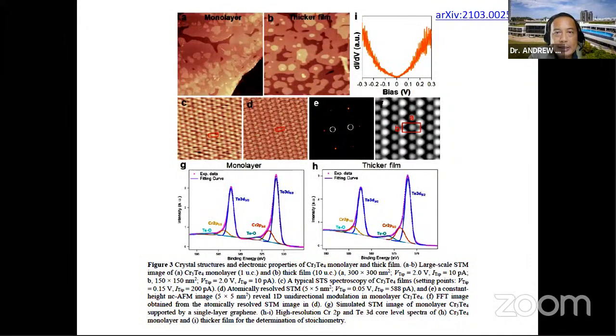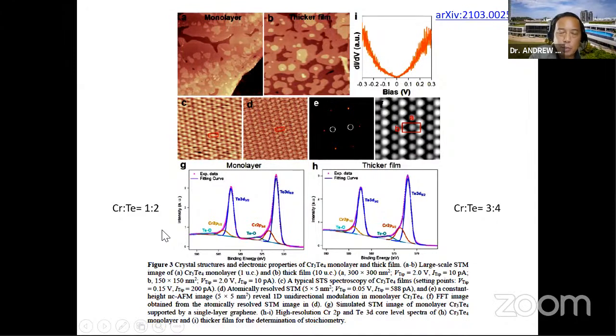And here is the XPS. I'll focus on the XPS, which shows the monolayer and the bulk. So from the XPS, we can get the stoichiometry. The thicker film has a ratio of 3:4 chromium to tellurium, and the monolayer is more 1:2, which is why we proposed the structure we saw 2 slides ago.